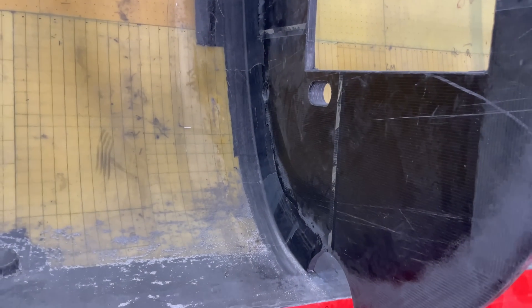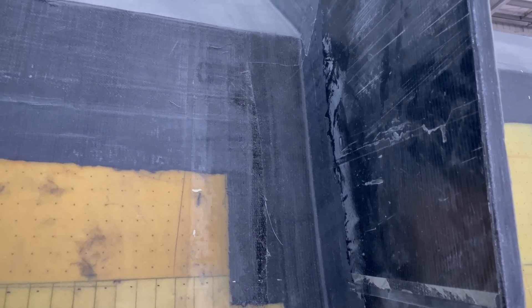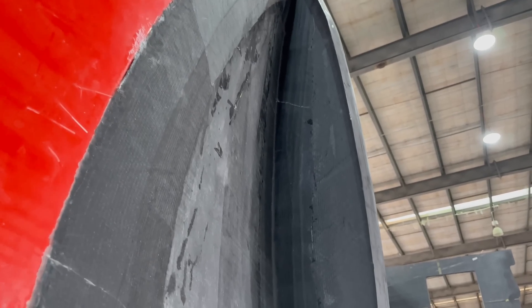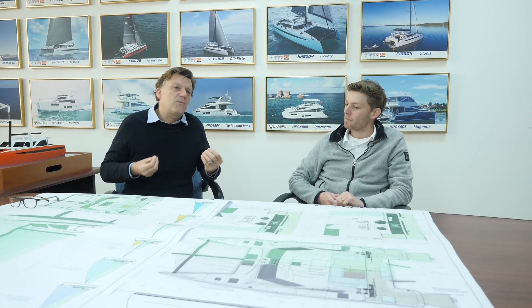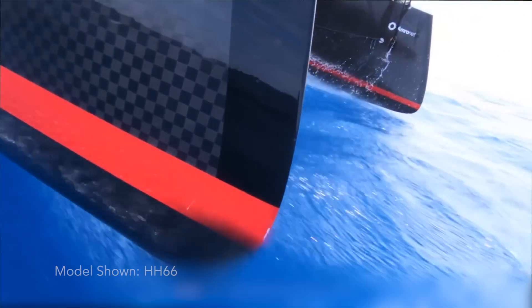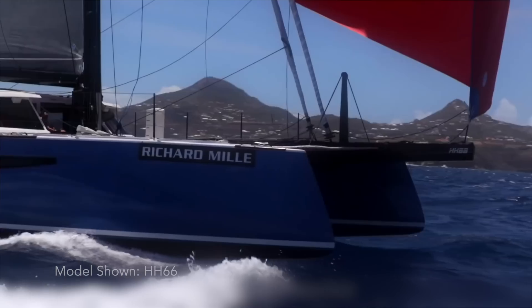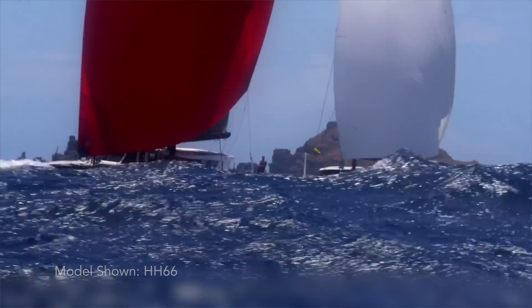All the structure is taped together with minimal amounts of glue. That's an important feature — all the bulkheads are bonded in using carbon taping, what we call secondary bonding, again with epoxy. That's far superior to any glue flange you could imagine, and very important for the longevity of the boat. These boats come with a five-year hull warranty and they're going to be sailing happily in the same form in 50 or even 100 years. Polyester boats just don't do that. Big tick for resale value and years of trouble-free sailing.